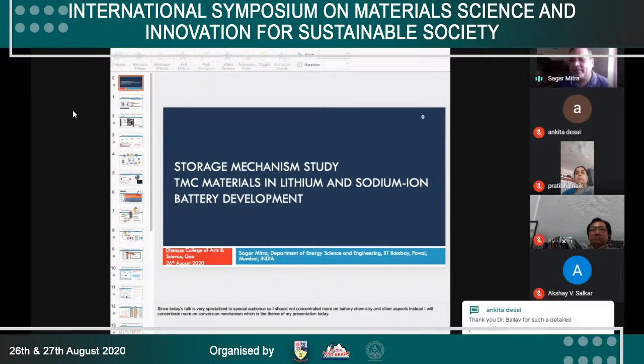The other concept is the million-mile battery, which came into the news, and even Tesla is trying it. What is the million-mile concept? Right now, the cathode we are using is not lithium cobalt oxide. It was introduced in the beginning of the history, but now other compositions, NMC and NCA, are used. They are the same, with the same structural features, only cobalt is replaced by nickel, manganese, even aluminum, so different terminology comes. But in most cases these crystals are polycrystalline. Now the million-mile battery claims that if I replace this polycrystalline NMC with single crystals of NMC, then I may have an increase in cycle number, and they are already working on it.